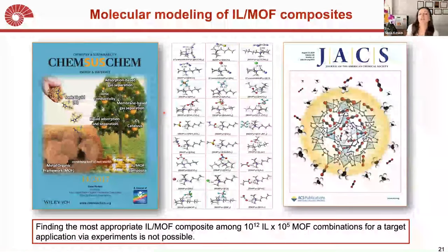Now, in the last 2-3 minutes, I'm going to talk about this. In collaboration with Professor Uzun, we have been preparing ionic liquid incorporated metal organic frameworks. I'm not the experimentalist, and I may fall short in explaining those, but obviously ionic liquids smaller than the pore size of the metal organic framework can be incorporated into the cage of the MOF so that you can reduce the pore size, and you can also change the chemistry, the environmental chemistry of the pore. In this way, by changing the pore size, you can selectively capture one gas molecule over another.